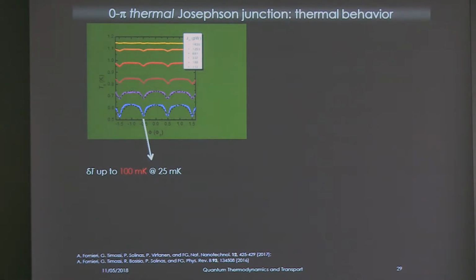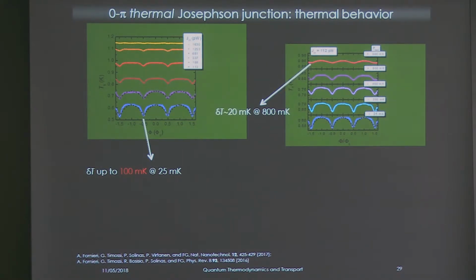So by changing the sign, we can increase enormously the full amount of heat that is transferred from one part to the other. And thanks to the superconducting nature of the structure, we were able to obtain very large temperature oscillation up to 800 milliK, due to the fact that the electron-phonon coupling is extremely weak also at higher temperature in a superconducting state.